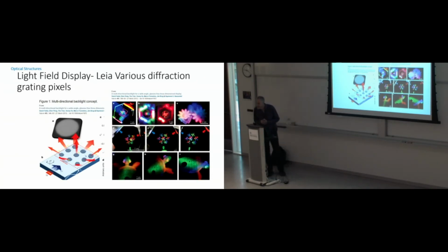Okay, yeah. Following up on that one, do you see any rounding of the features as you do this lowering of the levels, or do you actually manage to do it razor sharp? Well, there's a little bit. It's not completely anisotropic, so there is a little shrinkage down. That's sort of in the 0.1, 0.2 microns. So for our particular thing, I wouldn't claim that we do better than about 0.1, 0.2 microns, partly the undercut. If you don't do the self-aligned part, but do the other things, you can do much better than that. So you can do 10 nanometer kinds of features if you don't do the self-aligned part.